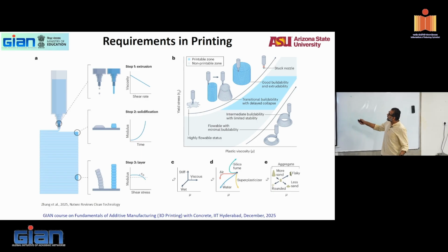Now, I put in a big band of where I can live. So if I have an extremely high yield stress with a very low viscosity, I know I can't print it, I can't extrude it, right? So forget it. If I have an extremely high viscosity with a low yield stress, yeah, I can really pump it, but I can't build it up, which means those are out of the picture. I kind of come up with a band like this. Now, within this band, what do I want? If I have a low yield stress with whatever plastic viscosity that I can consider, low yield stress, which means a highly flowable fluid, correct? Yield stress is that stress that is required to initiate flow. Lower that value, faster it will flow, correct?